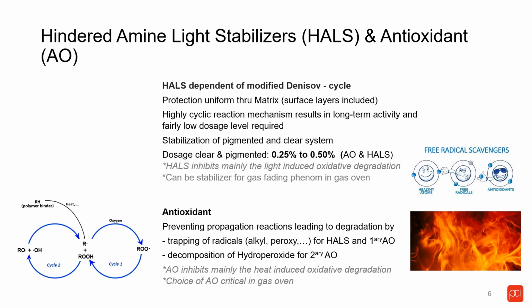And in regards to antioxidant, we have actually two types, the primary antioxidant and the secondary antioxidant. The secondary antioxidants, as you can see here, are mainly here to stop the degradation process of the hydroperoxide, where the primary antioxidant traps the radicals that are formed, the alkyl and peroxy radicals. In regards to powder coatings, very often we would choose one or the other. When cost is an issue, we will probably focus on a primary antioxidant unless we do a gas oven baking, and then we'll have to change to a secondary one, because the primary antioxidants, such as the 1010, for instance, the phenolic antioxidants, are known to cause strong discoloration in presence of NOx, which is about gas fading. But we'll talk about that later in our presentations.